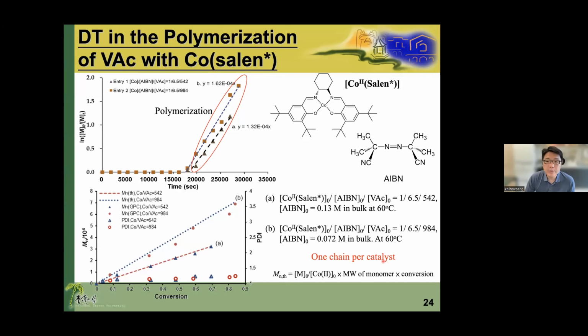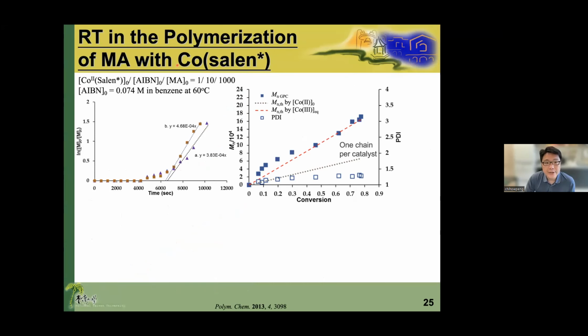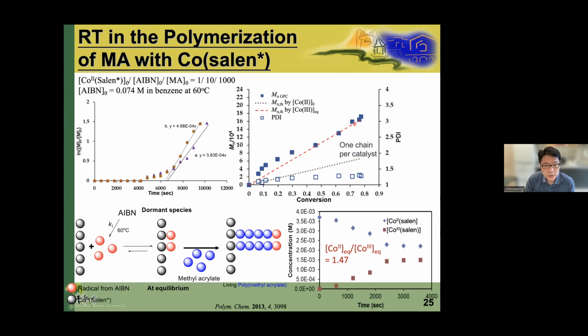However, when we apply this technique to methyl acrylate, we observe a little bit different phenomena. The same, we observe the induction period and the polymerization. However, the theoretical value calculated based on one chain per catalyst has a big deviation from the experimental result. And after we studied that, we understand that it is because when the radical is injected into the solution, still they